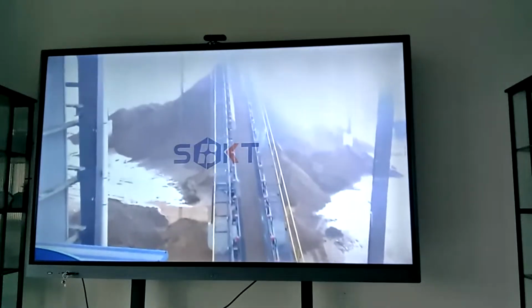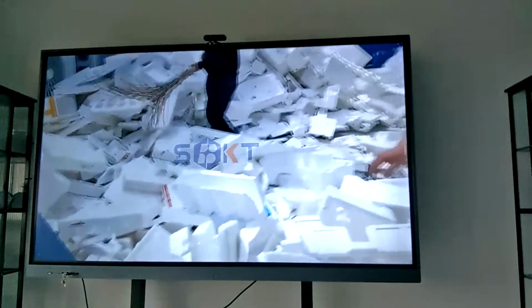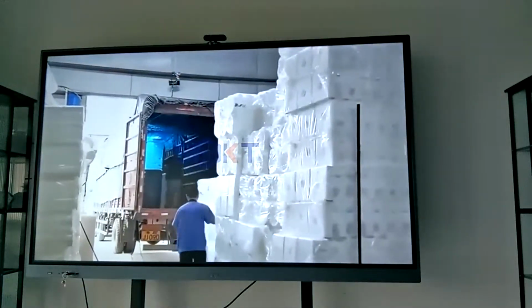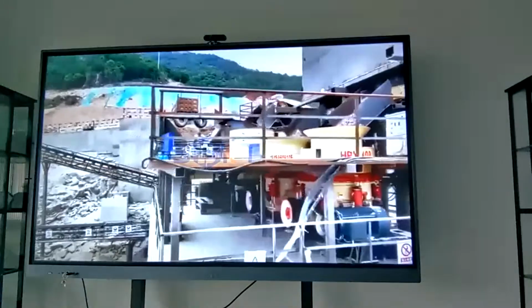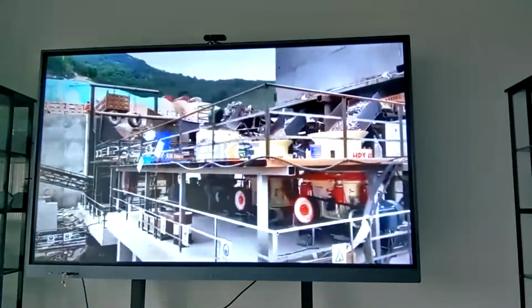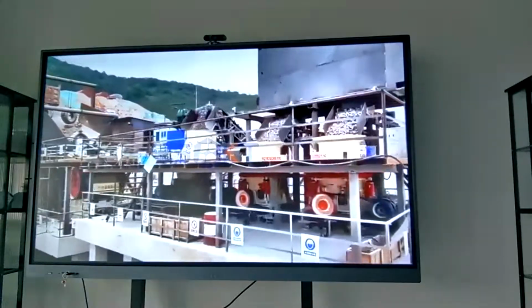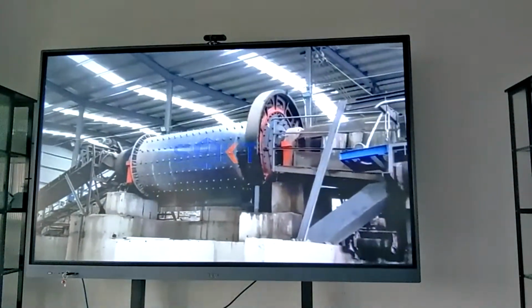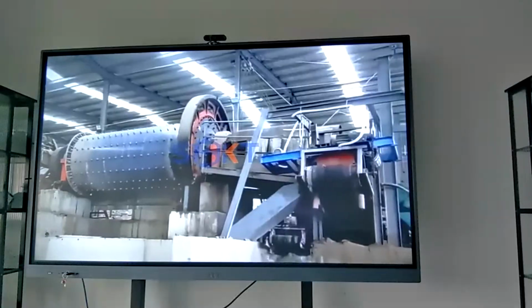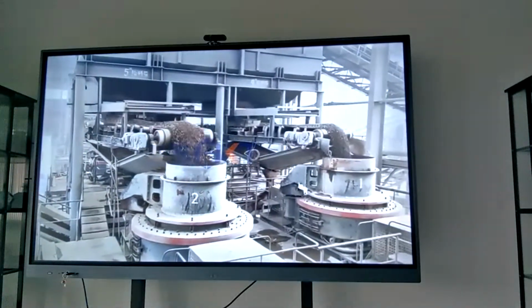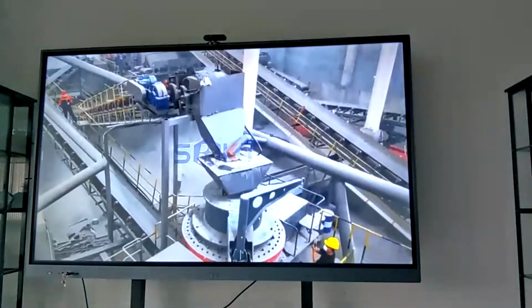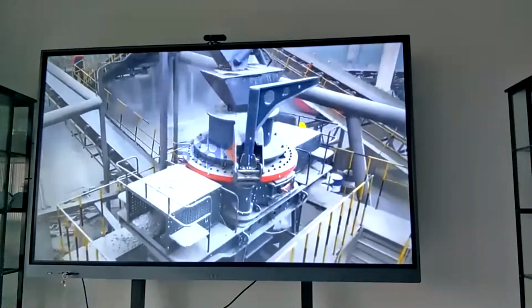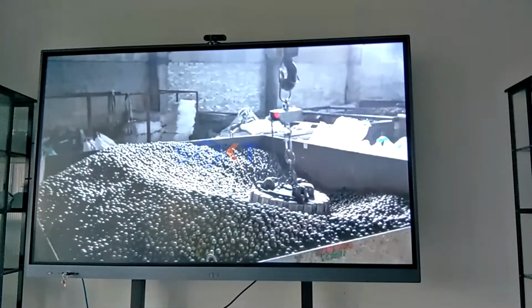Oxidized gold ore suffers weathering, the main characteristics being heavy leaching, loose structure, and well-developed fractures, with varying degrees of mud exposed on the surface. Grade is usually low, 0.3 to 2 grams per ton.